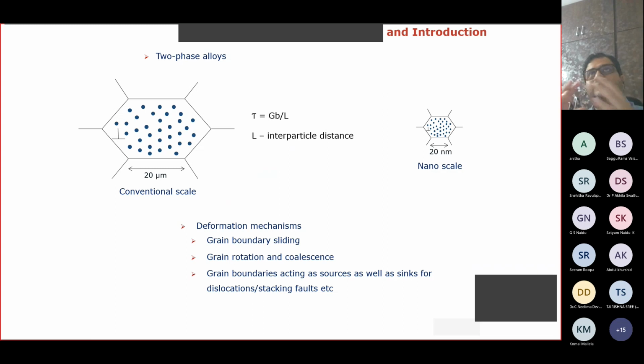And what I have talked about till now is the pure elemental metals, for example, aluminum, copper, iron, tungsten, molybdenum, and all those things happen there. But the moment you bring a smaller particle within the grain, this is a grain of roughly 20 micrometer size. You can also take it as 40 microns, no issues. This symbol shows the dislocation, and under the application of stress, this moving dislocation will get a lot of resistance by these precipitates, and the size of this precipitate, the distribution of these precipitates, and also the spacing between two neighboring precipitates also influence these mechanical properties.